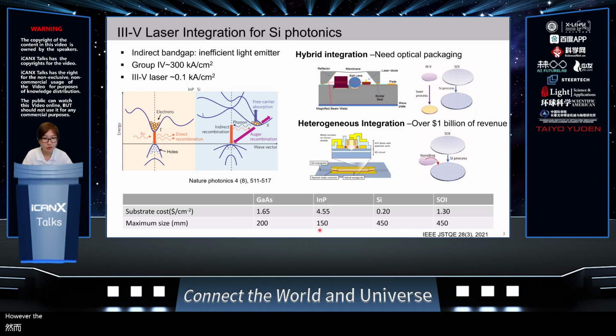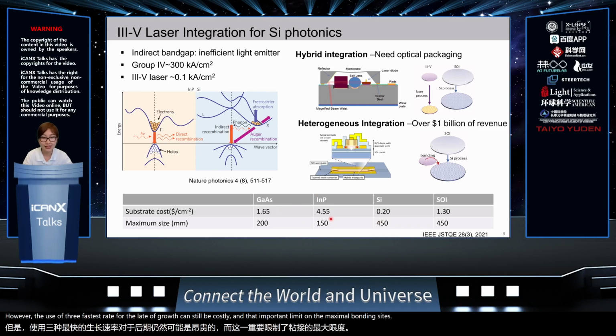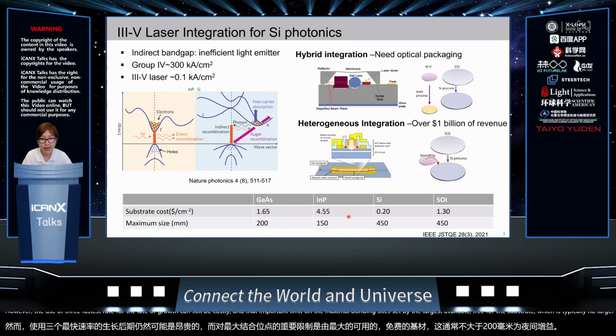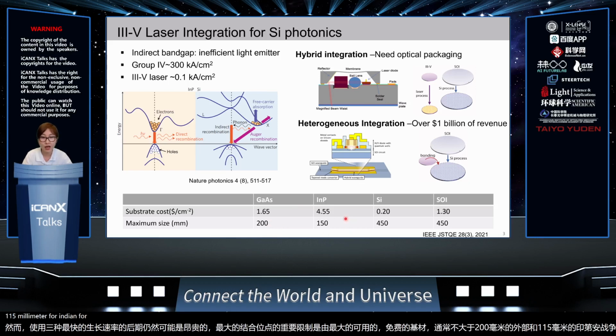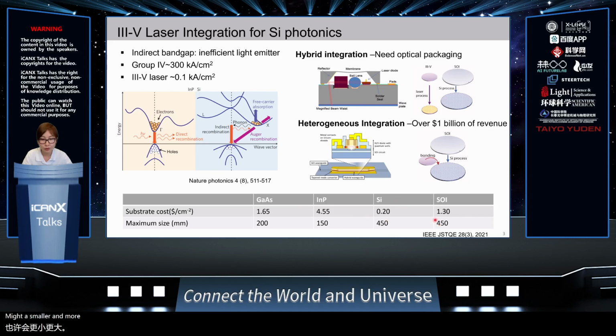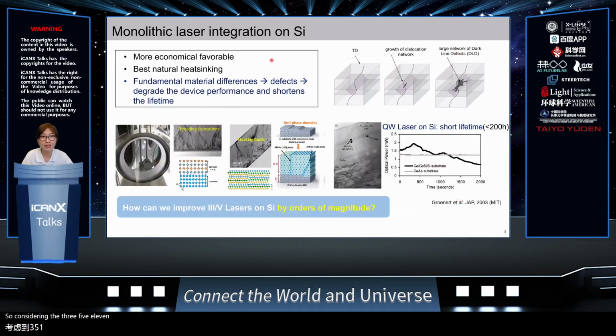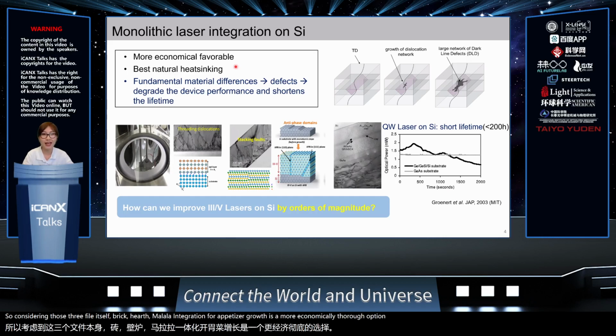However, the use of III-V substrates for the laser growth can still be costly, and that imposes a limit on the maximum bonding size set by the largest available III-V substrate, which is typically no larger than 200 mm for gallium arsenide and 150 mm for indium phosphide, much smaller and more expensive than the silicon counterpart. So considering the III-V substrate cost, monolithic integration through direct epitaxial growth is a more economically favorable option and also provides the best natural heat sinking for laser operation.